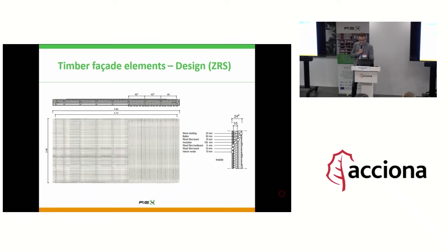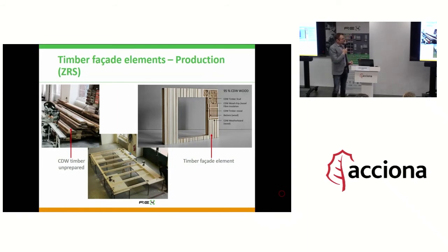And here you see in short the process from a pile of CDW timber, which, you notice from this pile, doesn't come from a recycling center, because of course this is not a small fraction. So this is reclaimed directly by selective demolishing of existing buildings. And by assessing the timber, by identifying damaged areas, metal fittings, and other things you don't want in your recycled timber, you prepare and cut in different ways and plane this material and construct.